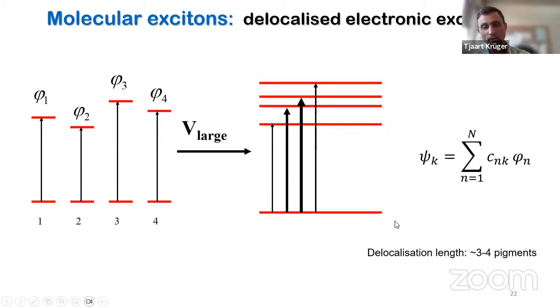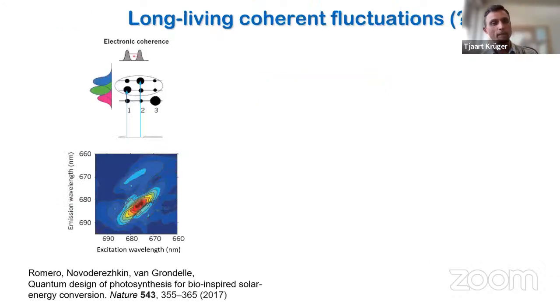Okay, and the typical delocalization length in photosynthetic systems is 3 to 4 pigments. That is because this creates a balance between the formation of the molecular excitons and the electron-phonon coupling. So electron-phonon coupling tends to localize the excitations, whereas these excitons tend to delocalize them. Okay, at this point, I would like to distinguish between these excitons, which are actually coherent excitations, and another type of coherent fluctuations that have caused a lot of hype in this research field. And that is the formation of electronic coherences, which are coherences between different excitons.